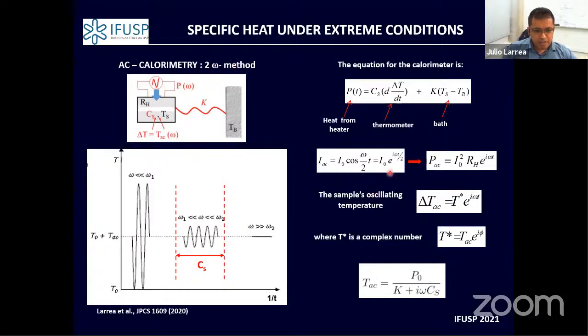If you make the calculation, you end up with the modulated temperature that you are measuring from your sample being basically related to your heat capacity. So by making this kind of simple measurement of the modulated signal on the sample, you can directly obtain the heat capacity of your sample. But the situation is not really that easy. Why? Because, as you see, it's a modulating technique, and we depend on the frequency that you apply in your heat dissipation.